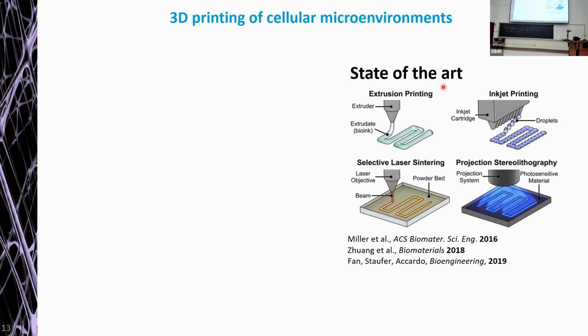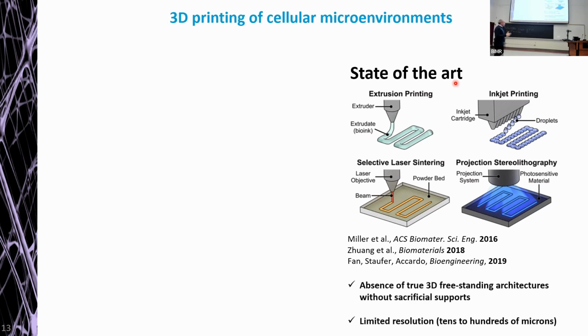that most of the approaches include techniques such as extrusion printing, inkjet printing, selective laser sintering, projection stereolithography, which are great approaches. For instance, using bioprinting or extrusion printing, you have access to a wide library of biocompatible materials, which is very important for 3D cell microenvironment. But these techniques also share some common drawbacks. For instance, the impossibility to create true 3D freestanding structures without the presence of sacrificial supports, and the limited resolution, which is usually ranging between tens to hundreds of microns.